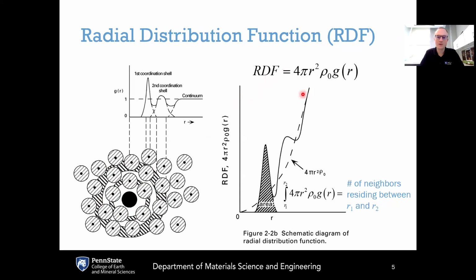Now, when the radial distribution function is approaching the parabola, that's the same thing as the pair distribution function approaching 1 and reaching continuum. At that point, you have just a complete randomization of the structure because there's a lack of correlation between the central atom position and the atomic positions at those large distances. So in that case, the g of r just reduces to 1, and then the number of atoms is basically governed by the number density, rho 0, and the limits of your integral between R1 and R2.